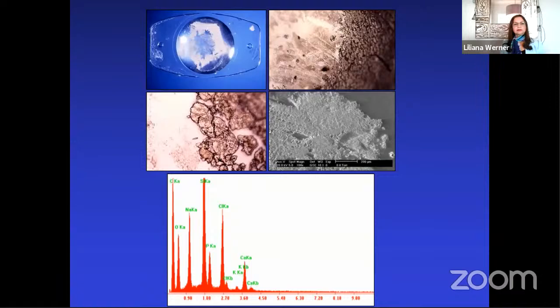Here you can see a plate-type silicone IOL that was explanted because of postoperative opacification. There are YAG laser pits on the optic, which indicates that the laser was used to try to clean the lens surface of the deposits, which are present only on the posterior optic surface. Surface analysis confirmed the presence of the elements calcium and phosphorus in the composition of the deposits.